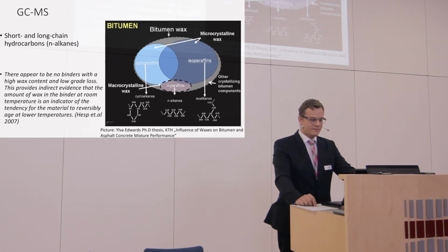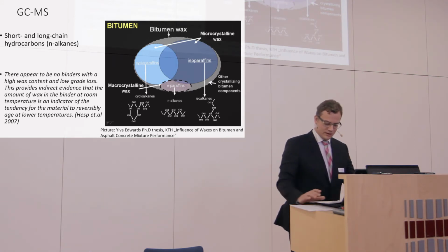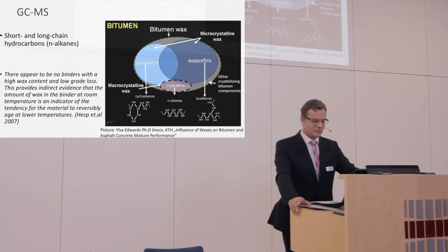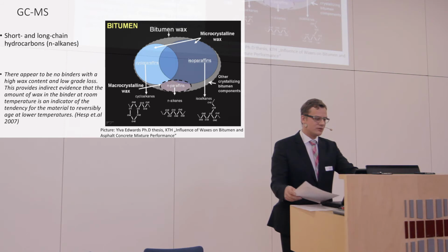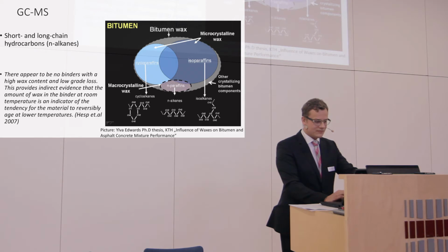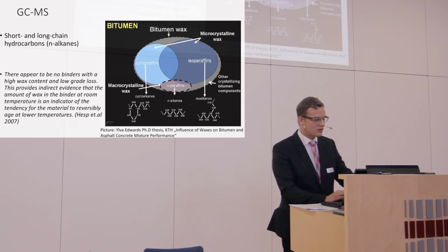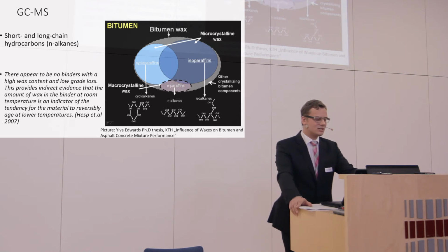Then we made a gas chromatographic mass spectroscopy study. There we show short and long chain hydrocarbon content. N-paraffins, which are long chain hydrocarbons, are inside wax and they tend to crystallize. From the literature, they appear to be no binders with high wax content and low grade loss. This provides indirect evidence that the amount of wax in the binder at room temperature is an indicator of the material's tendency to reversibly age at low temperatures.